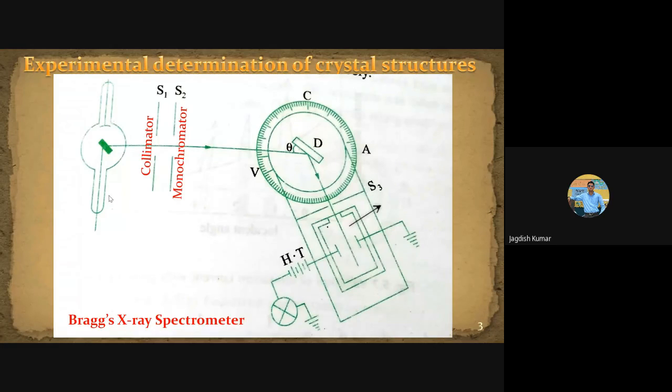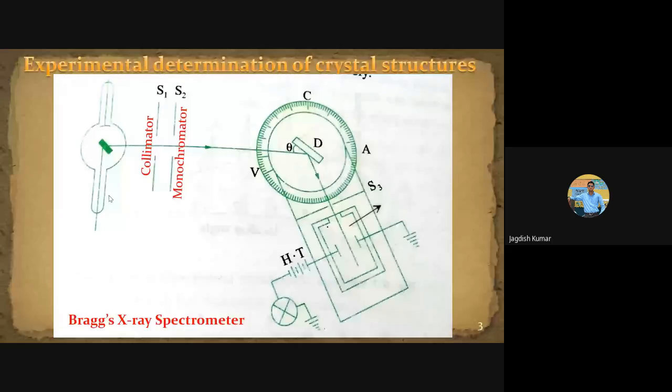So because of this, what will happen? There will be some broadening of the peaks. But broadening of the peaks can be because of many other factors, like size of the crystals. If crystals are of a very small size, like when you go to the X-ray diffraction pattern of nano crystalline samples, then you see peaks get broadened. So there are many other factors, but yes, the non-monochromatic nature of X-rays is also one possible parameter which can be seen for broadening.